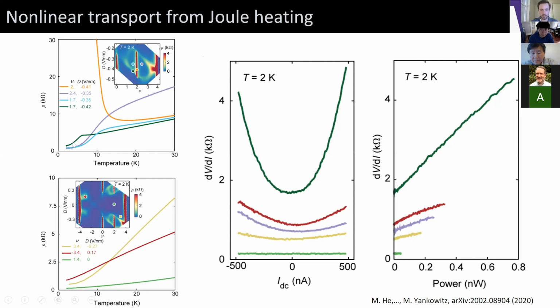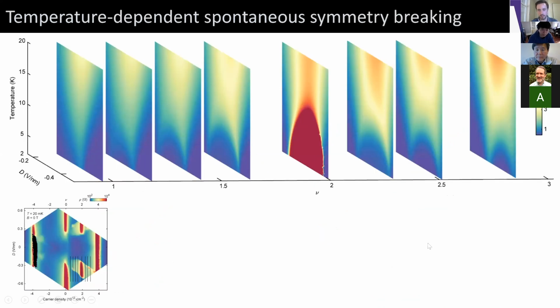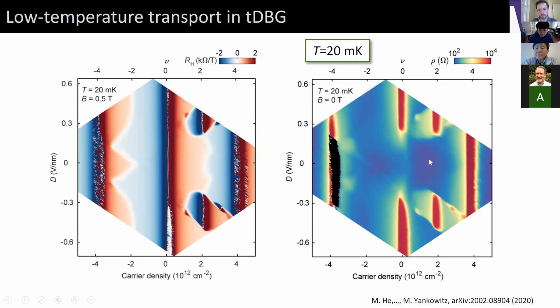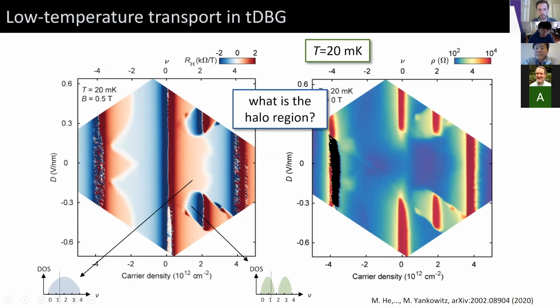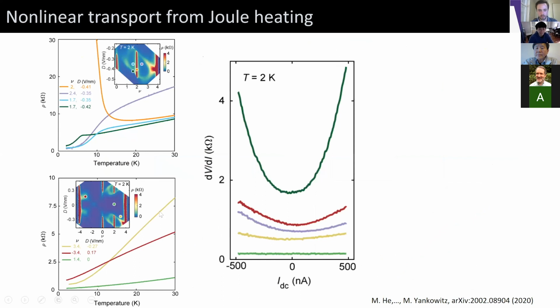And we also don't see zero resistivity anywhere. In fact, this halo region has higher resistivity than the metallic states surrounding it. If we just measure the DVDI in a metallic state, for example, this light green curve corresponds to this dot, which is squarely in a metallic state, then it is perfectly flat, as one would expect for a metal. But we're also able to measure nonlinearity in metallic states outside this halo region. For example, on the Van Hove singularity where the resistance is high, we also see nonlinearity. And if I just showed you the burgundy and the purple curve, you wouldn't be able to tell me which one is within the halo and which one is outside of it.